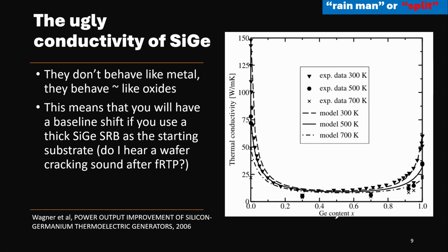So germanium moves one way, and the silicon moves the other way because they have different sizes. Imagine you have a pendulum model in your head. So when heat waves through it, germanium will act like a thermal blocker because it's big and it vibrates at a different frequency. So the phonon wants to travel through it, and it sees germanium blocking the road. That's the reason. A little bit of germanium will drop it like a rock. 10% is already dropped so low, right? Even a few percent will drop like a rock already. So that's a problem. Of course, I would call that a split, right? So that is damaging the property of this silicon germanium alloy.